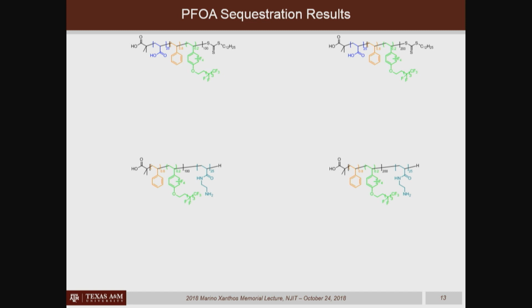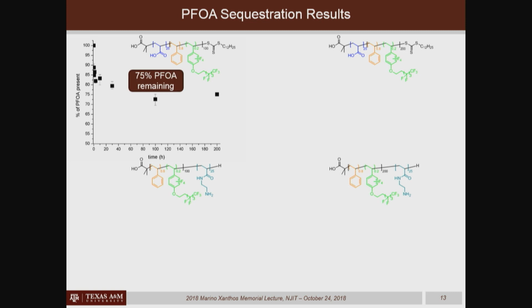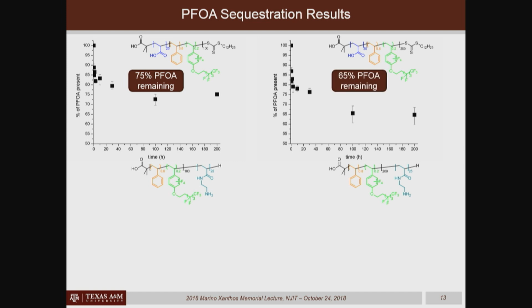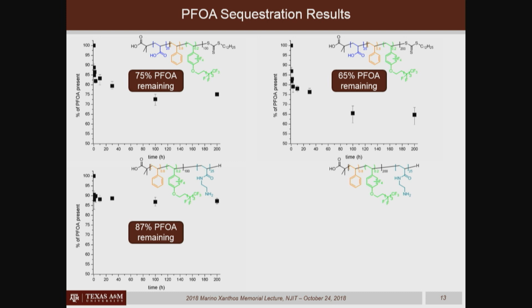And what she found is that for the two polymer materials that have the polyacrylic acid segment, in one case she was able to recover 25% of perfluorooctanoic acid. In the other case, 35%. In the cases where the amino group was present in the shell, we thought those were going to be better at capturing the perfluorooctanoic acid. They actually turned out to be less able to capture the perfluorooctanoic acid.